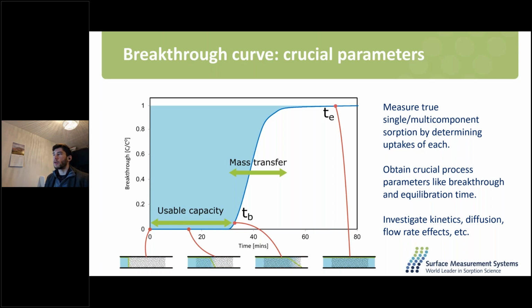But it also gives you a little more information about process parameters. If you're thinking about something like a filter for toxic gases, you don't want to study the total equilibration time. What you want to know is when you start seeing the toxic gases coming out of the filter. So this is more important from the process side. The breakthrough time is more important for the process side than the equilibration time. And the shape of the breakthrough can give you information about mass transfer and kinetics of the particles and of the adsorption.